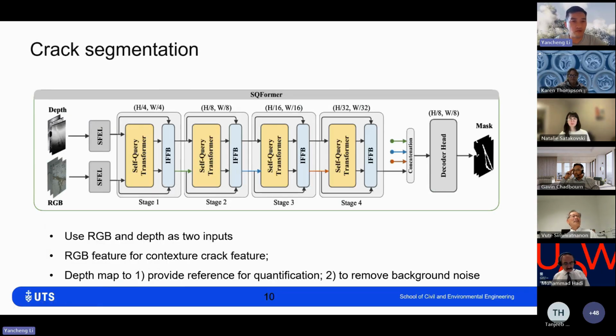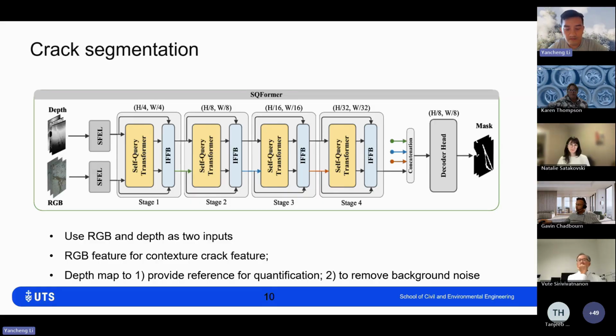So the overall framework here is that we are using two pipelines, the depth image and the RGB image. We go through different stages of feature extraction, and also feature fusion, to combine them together. Why do we use depth maps? The depth map, as mentioned before, first provides a reference for quantification. We need the distance from the camera to the crack surface as the reference measurement for quantification.